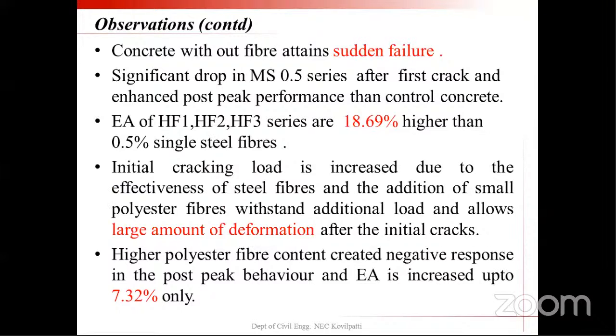Concrete without fiber, 0% fiber, causes sudden failure, whereas in the other series a large amount of deformation takes place and failure is very gradual. And you can see the energy absorption capacity is 18% higher than the single FRC. Initial cracking load is increased because of the steel fibers, and the polyester fibers are able to withstand some additional loads because it is a low modulus fiber, but it will allow a large amount of deformation. Polyester fibers play a role in allowing large deformation, even after the matrix has cracked. With high polyester fiber content, sometimes negative responses are also observed.